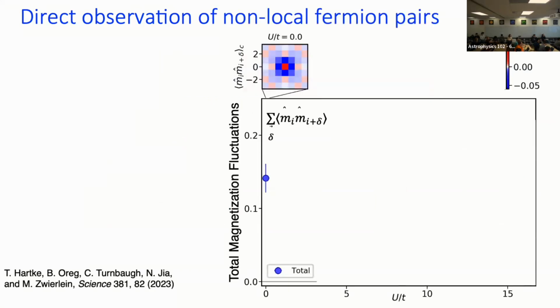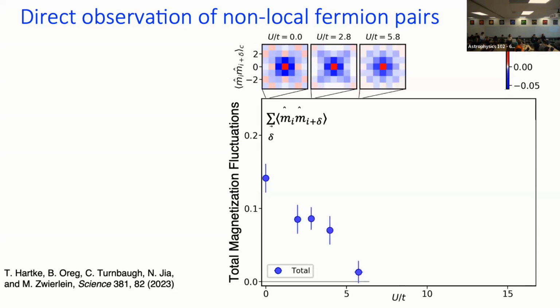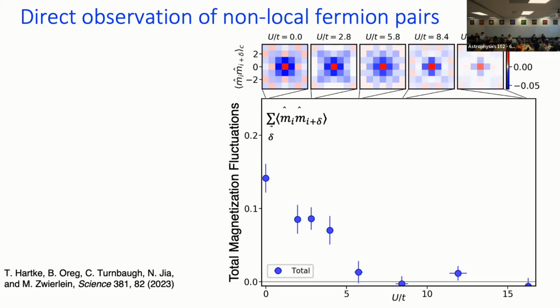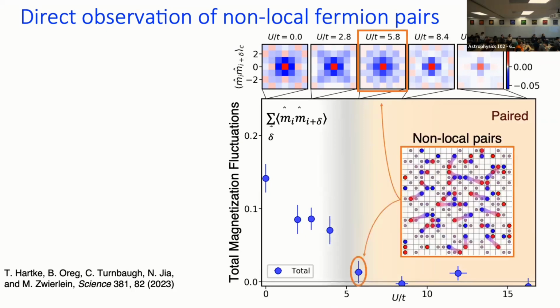And we can sum up these images to get the total spin fluctuations. And for the super duper experts, this is equal to the spin susceptibility times the temperature. So for any finite temperature, which we unfortunately have, seeing zero spin susceptibility is also directly telling you that you have a paired gas. So we see that spin susceptibility go to zero at some interaction strength. It's not a critical interaction strength, it's just the interaction strength where at our temperature, we start to exponentially suppress unpaired atoms. So that's the idea.